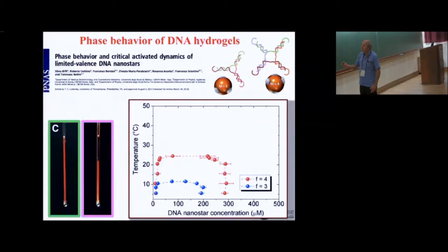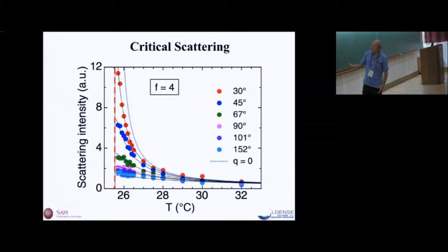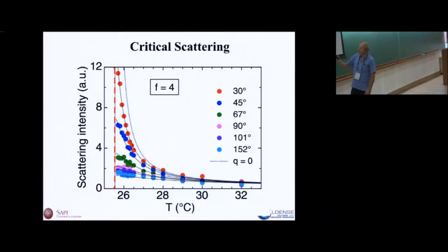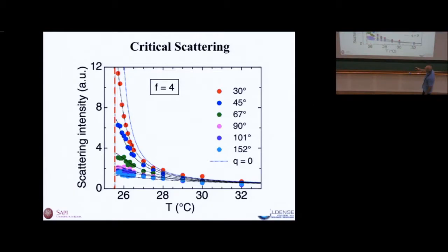If you go here and look at the fluctuations, you can measure them with light scattering, and those are the results at different angles. The lines are what you would predict for a critical phenomenon. This is very close to the critical point. This is a Lorentzian function, and you see how nicely the data are described by the theoretical expression that you expect close to the critical point. You see the divergence of the scattering intensity at low temperatures.